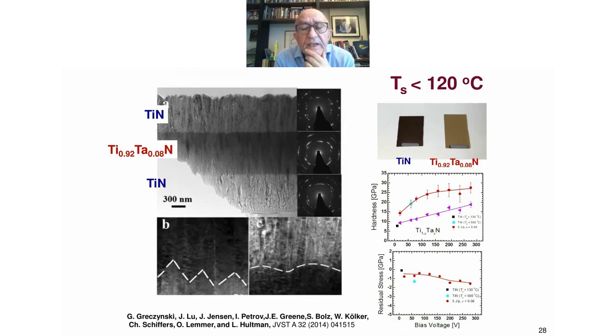Now, you see up there, titanium nitride without bombardment is black, absorbing. The one with 8% tantalum is kind of shiny and golden. And you can see in the cross-section the effect of starting the tantalum bombardment. So the bottom part of the film is pure titanium nitride at floating potential. And in image B, you can see the tops of the columns from the bottom interface. They're sharp. And as soon as we start the tantalum bombardment, the nanoporosity in the columns disappears, and the porosity between the columns persists until we smoothen the top interface.